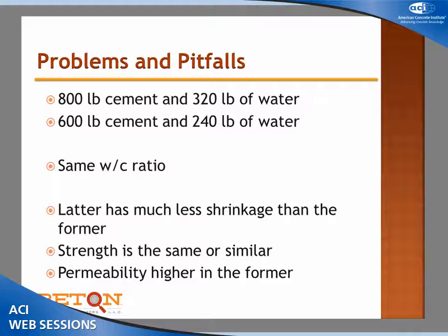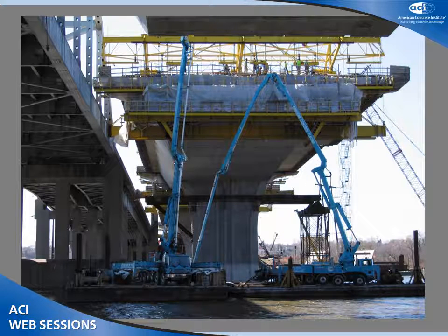Here's a couple of concretes. Both of them have a 0.40 water to cement ratio. The 600-pound, 240-pound of water mixture, that's going to shrink a lot less. Strengths will be same or similar, maybe a little bit higher for the second one. The permeability is going to be higher. Permeability is going to be higher at a fixed water to cement ratio, because most of the permeability occurs in the paste fraction, and you've got lots of it in this mixture. And then we get to the other perennial favorite.